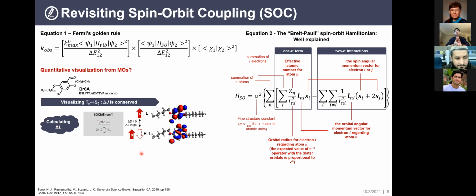So how can we visualize this orbital angular momentum change? For instance, in the very popular BrBA phosphorescence material, in its, let's say, HOMO-1 to LUMO transition, which is going to affect the spin-orbit coupling from the T2, the second triplet state, to the ground state. And this actually, from the calculation, has a somewhat large spin-orbit coupling efficiency, which is because you have an in-plane electron in the hole and an out-of-plane electron in the z direction in the electron orbital, which is the LUMO orbital here.